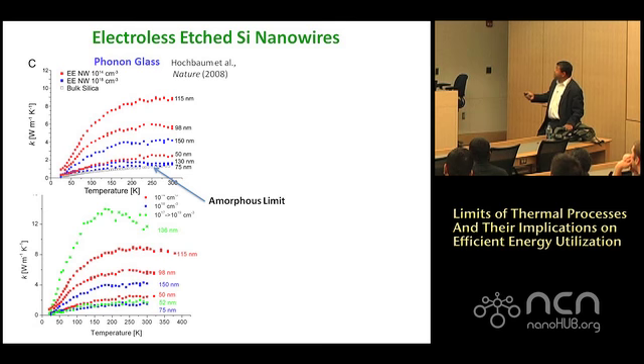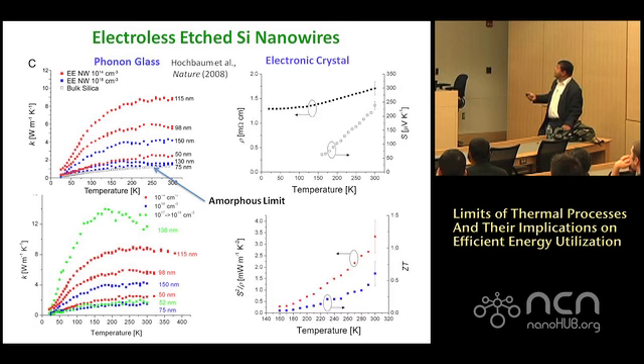What we also found in some of the wires, this is thermal conductivity as a function of temperature, some of the wires, depending on the doping level and the roughness, approached the amorphous limit in a crystalline wire, which was totally mind-boggling for us because we never expected that. And one would not expect that. And as a result, the ZT shot up to about 0.6 or so, and that turned out to be quite interesting because now we're within the range of hitting the target of 1 and beyond.